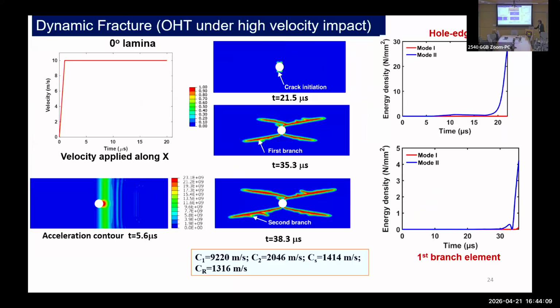Okay. As I was telling before, we were doing a lot of dynamic events. So instead of pulling the specimen quasi-statically, we applied a high velocity impact. So it's an impulse: 10 meters per second velocity was applied in 1 microsecond and then held for a long time. This is how the wave propagates across the domain. What we see here are several different phenomena: 4 cracks initiate from the hole edge, all of them simultaneously propagate, and then lots of branching starts happening, which is a very well-known phenomenon in dynamic fracture behavior.